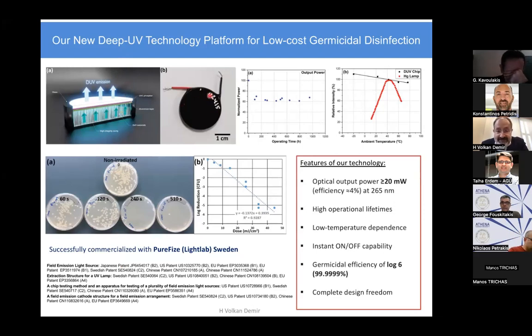This is the actual device fully fabricated. You can see it is several centimeters laterally and sub-centimeter thickness vertically. We can make at the moment 5 millimeters in thickness. And inside this device, what we have is high quality vacuum cavity. And in the cavity, we have nanostructures that are specifically designed to emit electrons efficiently under high bias, but low current density. So this device actually working under high bias, but using low current density requires low power.